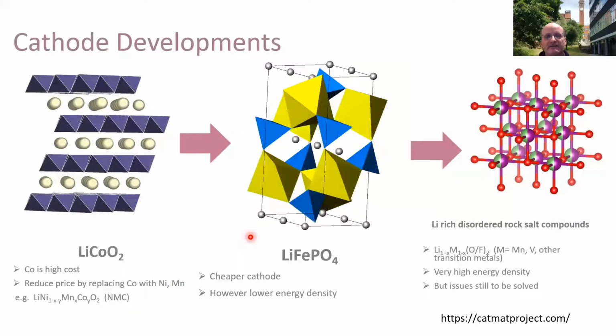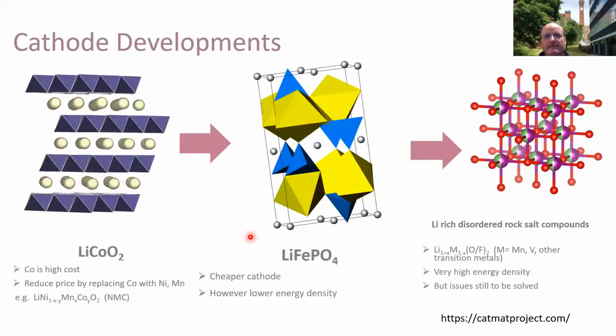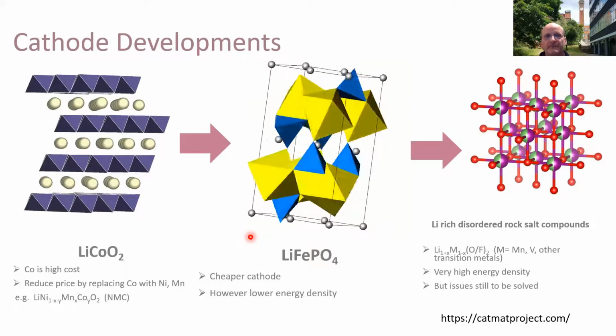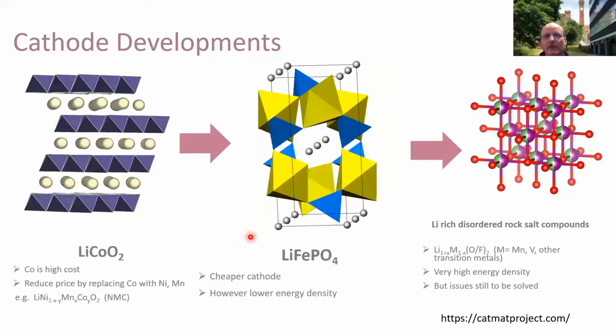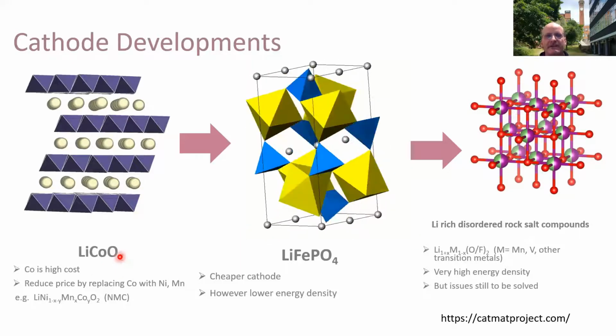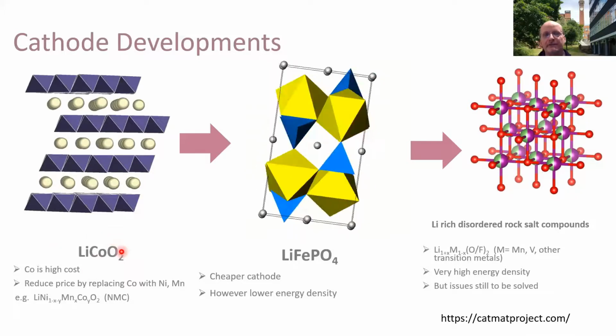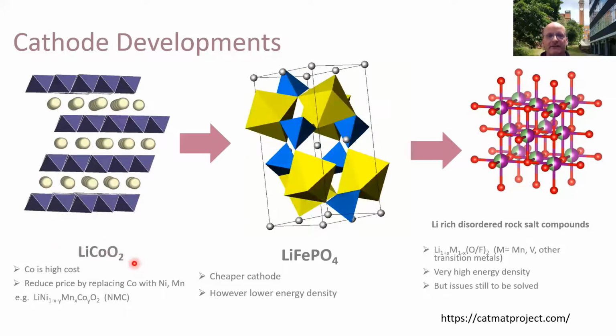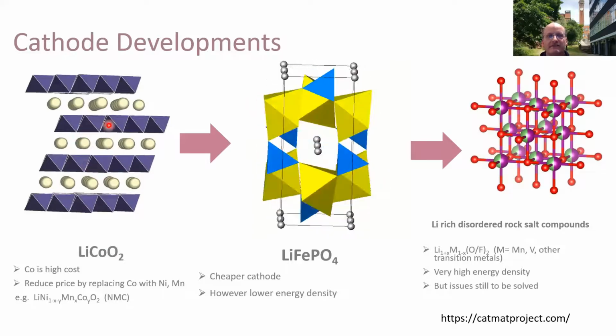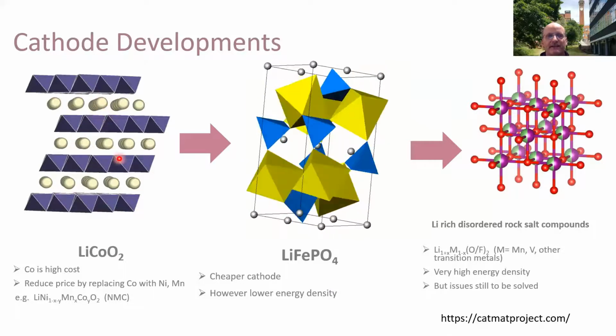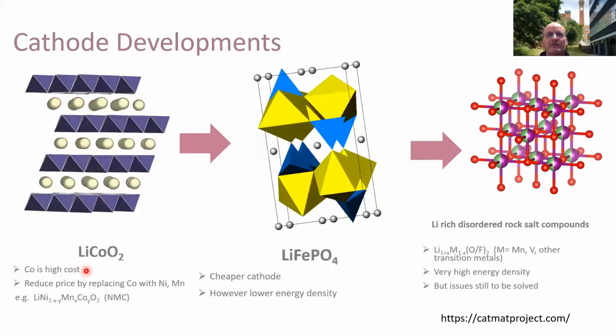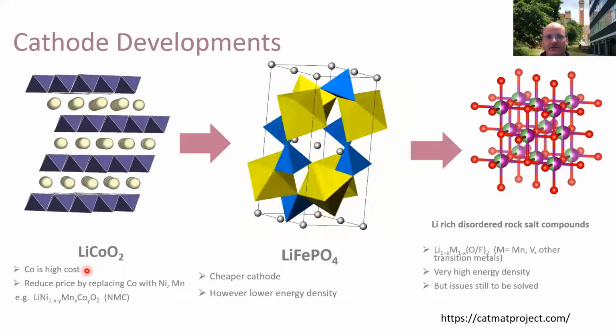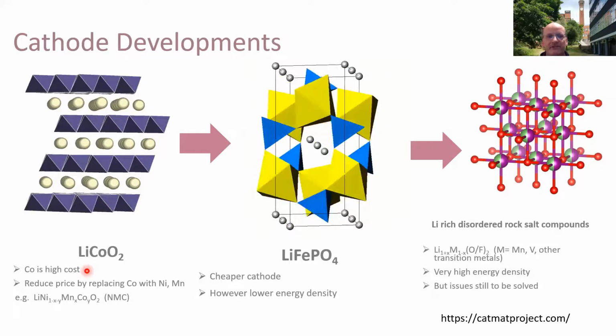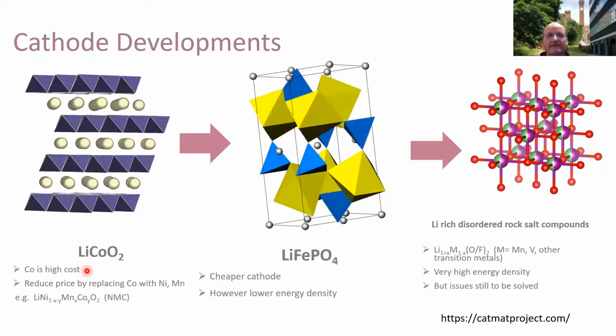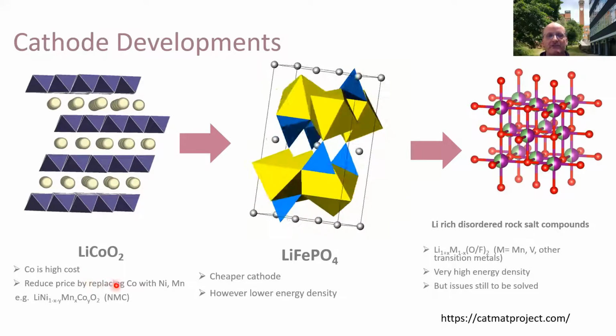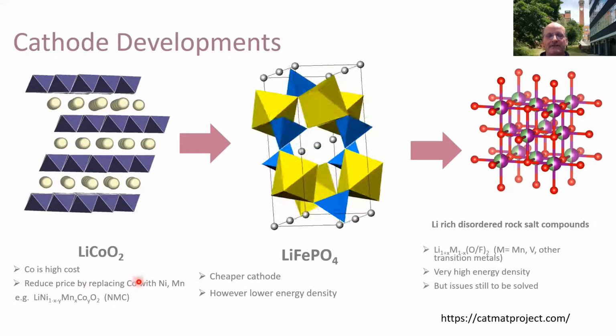Okay, so I mentioned the key things that we need to optimize our energy. So what are people working on? The original material that Goodenough looked at was lithium cobalt oxide. It's got this layered structure that I mentioned earlier with lithium in between the layers. And the issue is cobalt's high cost. There's also concerns regarding the sourcing of it from the Democratic Republic of Congo. And so there's a lot of interest in replacing the cobalt with other elements.